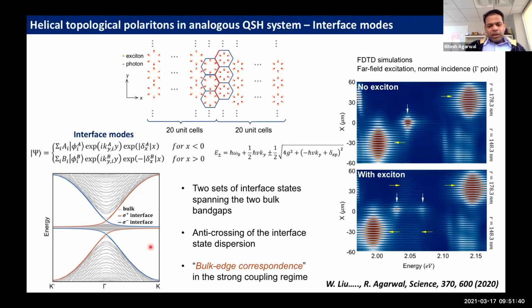Interestingly, in this polaritonic regime, when the system is topologically non-trivial, a photonic Dirac cone splits into two Dirac cones, as you can see here. This has everything to do with the light matter coupling strength. We can solve the bulk and obtain the coupling strength of the system. At the interface modes, the splitting of these two Dirac cones is a function of this light matter coupling strength. Roughly speaking, one can say this is an observation of the bulk edge correspondence.